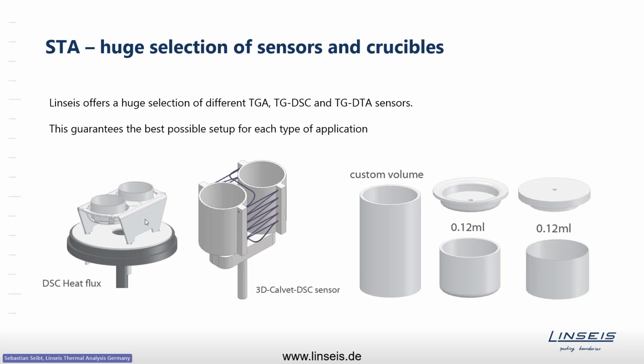If you want to run bigger sample amounts, we also have a so-called 3D DSC sensor, which allows the use of bigger amounts. It does not follow any ASTM anymore. However, it allows you to run up to 1 milliliter sample volume. It requires a somewhat complex calibration, but it works. And if you have a very inhomogeneous sample, it sometimes has the advantage of a little higher resolution than the classical 0.12 milliliter standard DSC heat flux sensor head.